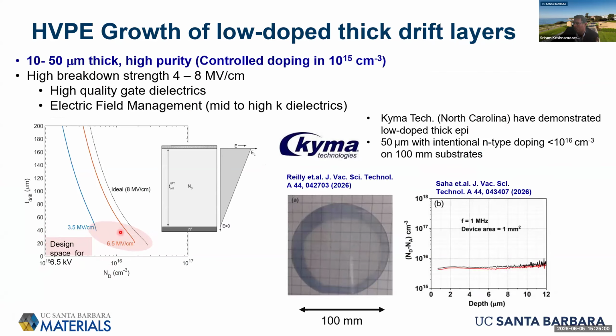And in the ME Commons program that we have with the CLOS hub, Kyma Technologies was the lead for that project. They've been able to get some outstanding results, domestic EPI results. So these have been published very recently in the special issue on gallium oxide just this month. This is a paper from Carolyn Riley and Jacob Leach at Kyma. They have been able to demonstrate up to 50 micron thick epitaxial layers using halide vapor phase epitaxial growth.